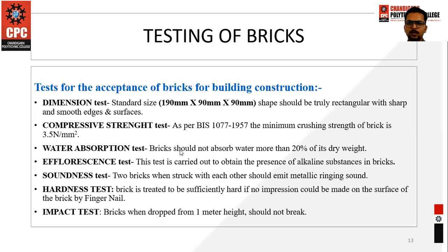After that, you have to immerse the bricks in a water bath for 24 hours, at normal temperature, 27 to 30 degrees. Keep them immersed for 24 hours. After 24 hours, you weigh them again. The difference between those weights should not be more than 20% for a first class brick.